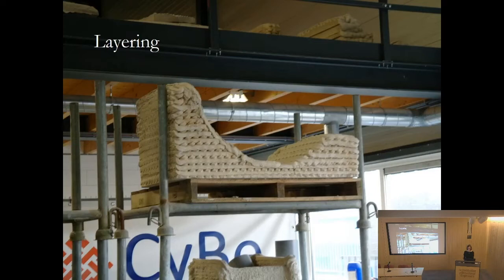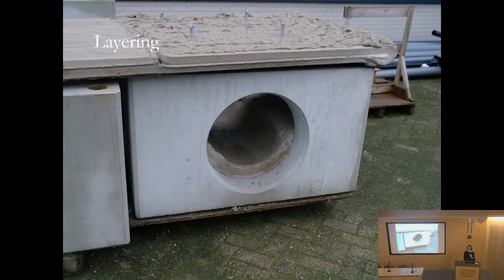The same company was also looking at producing sewer pit connections. In the Netherlands, these are built up with brickwork underground, meaning removal takes a long time and requires closing the road. Each one is individual. With 3D printing, you scan the pipes, understand what's there, print the supporting material in concrete, insert it into a precast concrete element, and put it in within a day. They estimated an 80% time saving because of this.